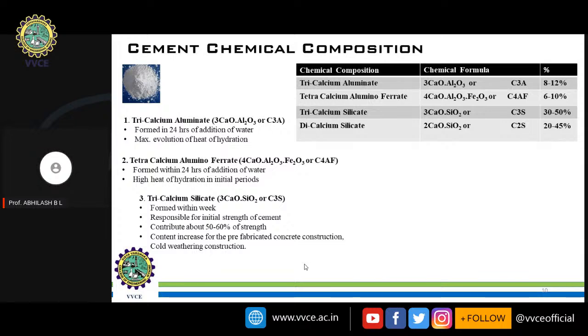Right? Tricalcium silicate is formed within a week and is responsible for the initial strength of the cement. You need to always remember C3S: the initial strength of the cement is obtained from the chemical compound tricalcium silicate. It contributes about 50 to 60% of the strength of a concrete. Fine. The majority of the strength, that is half of the strength of the concrete, is achieved from tricalcium silicate. Its content is increased for pre fab concrete construction and cold weather construction. Like this, you can segregate this type of chemical content based on the application of a cement.